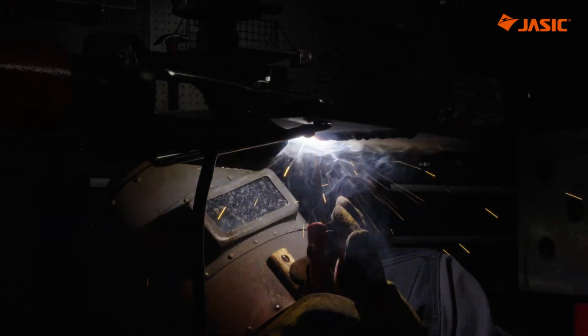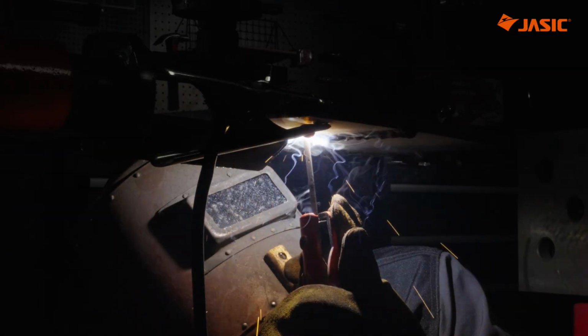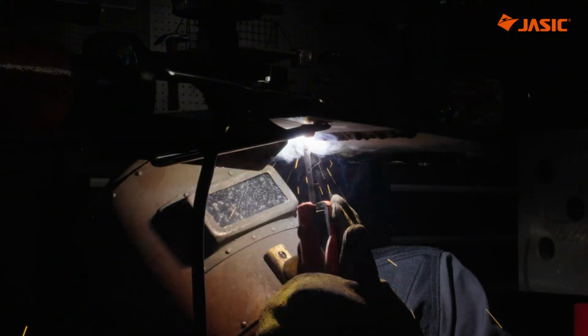You can also listen to the sound. If you hear a slight breakthrough from the backside, stop the arc and wait until the pool cools down to a dull red before continuing. Throughout the process, use the electrode to hold the molten pool in place. This helps prevent it from dropping while avoiding concavity on the backside.